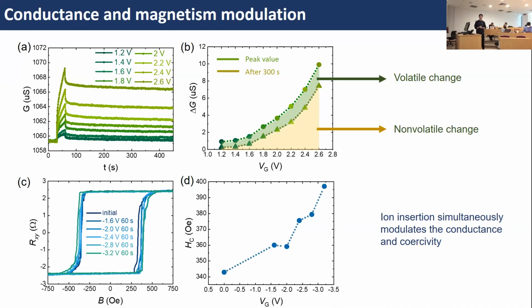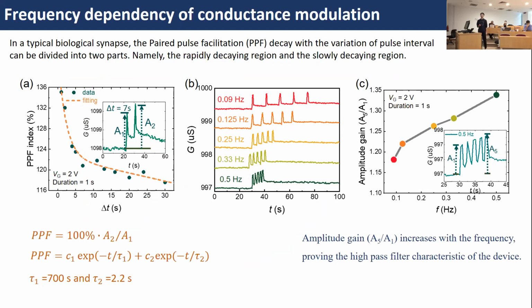So it means that the ions being trapped in the films can simultaneously modulate the conductance and the coercivity, which just brings in another dimension of a synaptic transistor, because usually it only modulates the magnetism or it only modulates the resistance. Okay. And then to simulate a biological synapse, the paired pulse facilitation is quite important. Here we apply two consecutive pulses and then calculate the paired pulse facilitation index according to these equations, it will show two indexes, the tau1 and tau2.